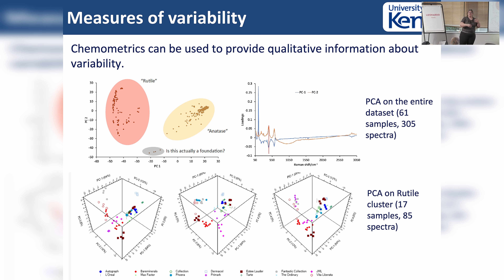The PCA is important because it's now starting to look at where and at what level the variability is. We can take this systematically through principal component one, principal component two, up to a point where you almost see a flat line where there's no longer any variability. That's important because if you can start to track the variability you can start to identify where it comes from. The cluster plots allow us to put this into three-dimensional space, and when you look at it like this we find it very hard to discriminate between samples beyond clustering - so from a forensic point of view, not so good for matching, although we can tell if it belonged to a particular family.